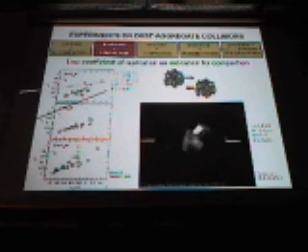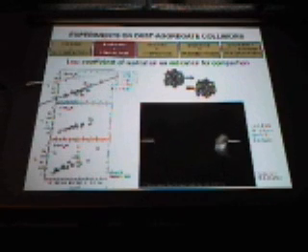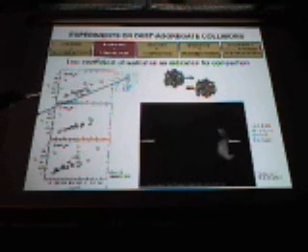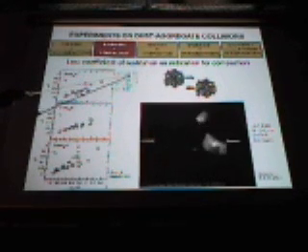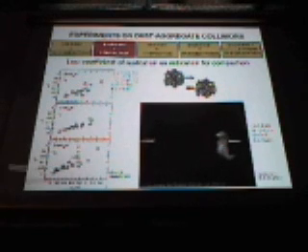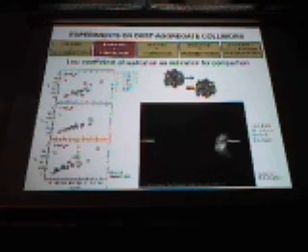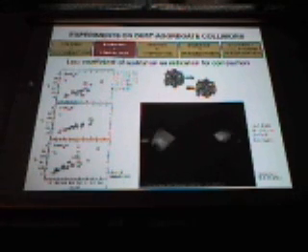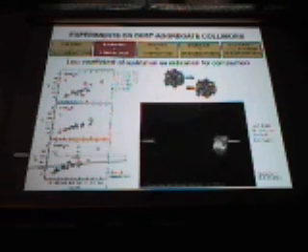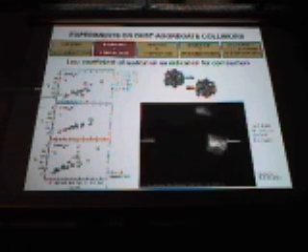At a little lower velocities, Blum and Münch did some similar experiments in 1993 at 15 centimeters a second, 50 centimeters a second, and 1 meter a second relative velocity with different particles. So this again is SiO2. Here there's zirconium silicate, and what we observe in these experiments, as well as in these experiments, is a coefficient of restitution which indicates compaction.